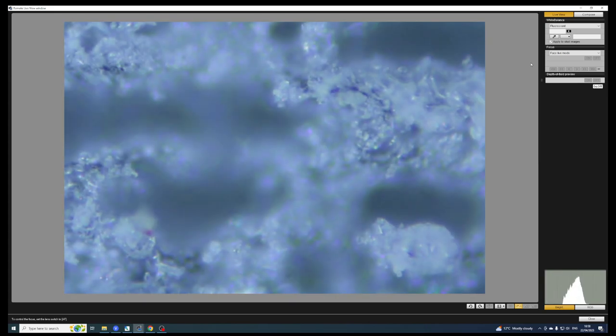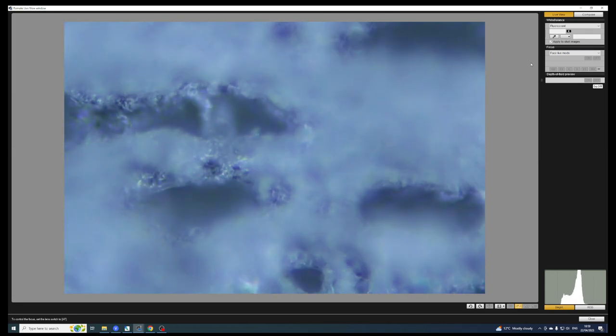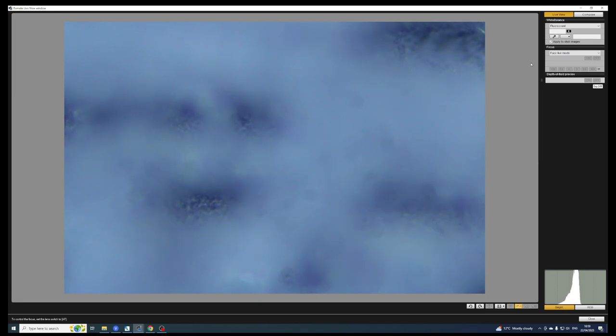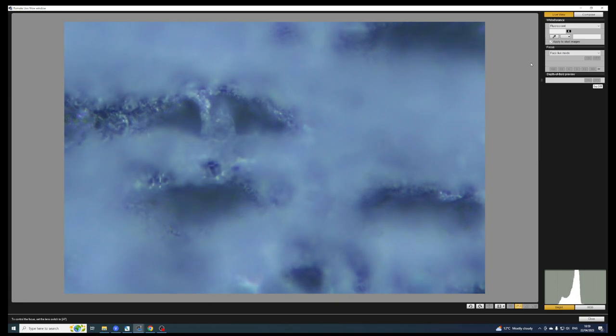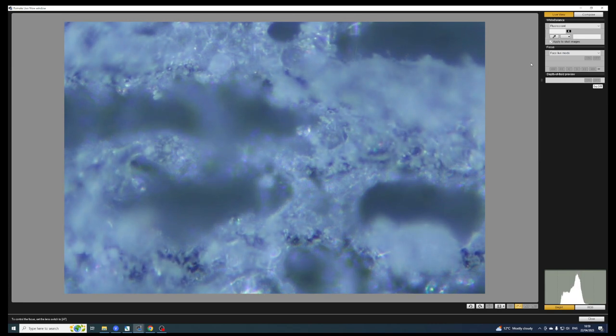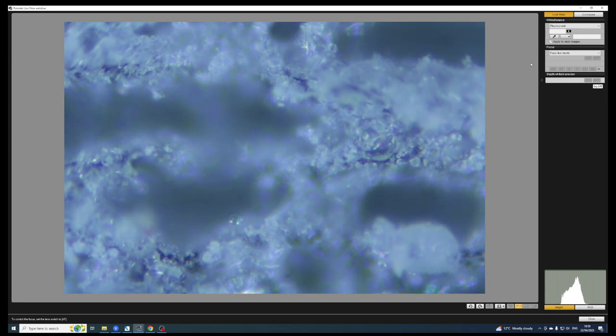All right we've now up above the surface and we're going into fresh air. If I change the magnification back a little bit we should see them a little bit clearer. But you can see that there's still huge depth there. Look there's a hole in the bottom but even in the bottom it's full of bubbles. And then I'll draw down and we'll pull out of the hole and we come up towards the surface of the material. And as we come up towards the surface of the material look bubbles bubbles everywhere bubbles. As I tried to explain to you before that's the cause of all of our whiteness that we perceive. There is scattering of light everywhere in this material.